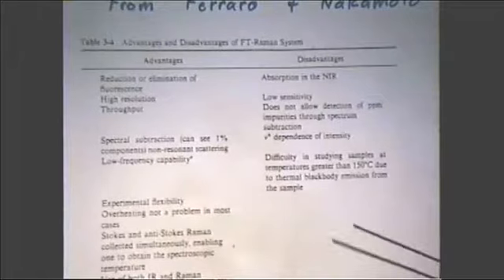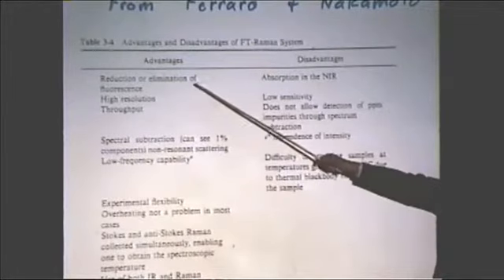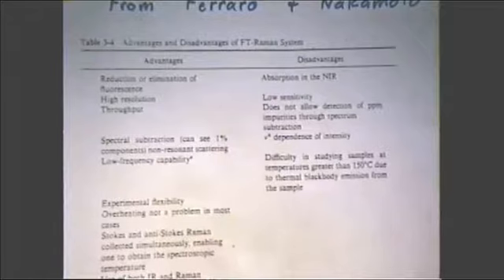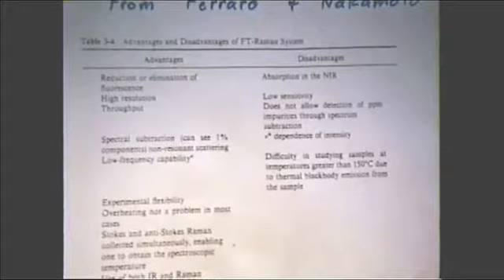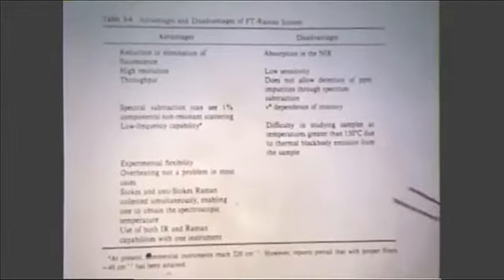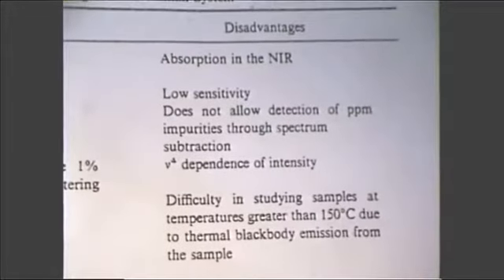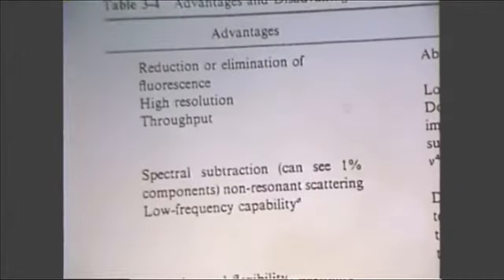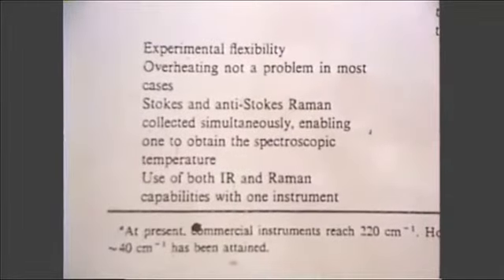So this is just a table or a little graphic from the book by Ferraro and Nakamoto. It talks about the advantages of so-called FT Raman, which is near-infrared Raman. And they comment on the fact that it reduces or eliminates fluorescence. But then they also say that there are some disadvantages. In particular, oftentimes you have absorption in the near IR, so that if you're looking at a colored sample, you can't do Raman scattering from it because of this absorption. Another problem is that the Raman scattering intensity goes as the fourth power of the frequency of the light that you're using to excite the sample. So when you go from the visible to the near IR, where you are lowering the frequency by a substantial amount, you're also killing off your Raman scattering because of this fourth power dependence.